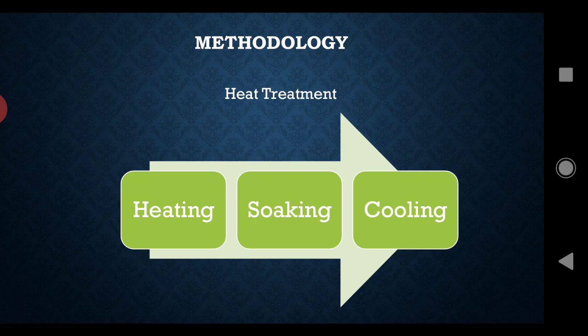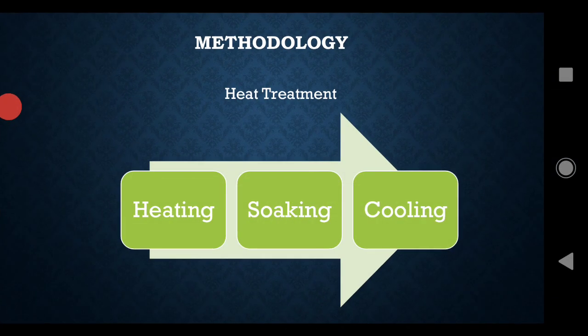And the second step is soaking. After the stainless steel part has been heated to the desired temperature, the soaking time depends on the mass of the specimen. The greater the mass of the specimen, the longer it must be soaked.